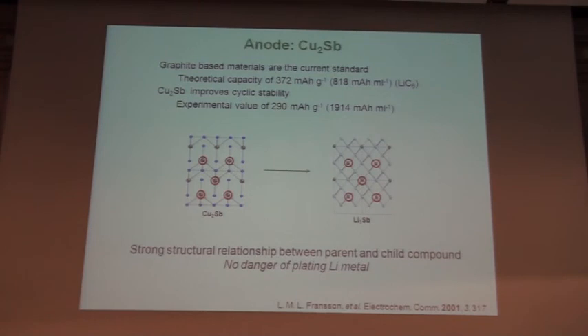Antimony is not completely environmentally safe, although in this compound it is very stable, so it's not leached out of the compound. But unfortunately, we can't avoid using antimony because it's required for the physical properties of this compound. And what's important is that, again, it lithiates about 50 millivolts more positive than the plating of lithium metal, so it's quite a bit safer than graphite.